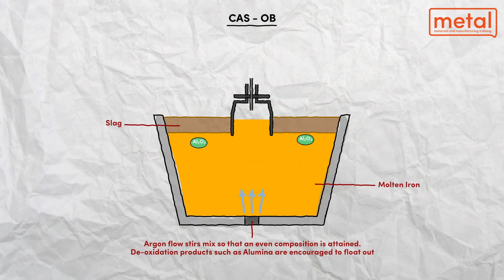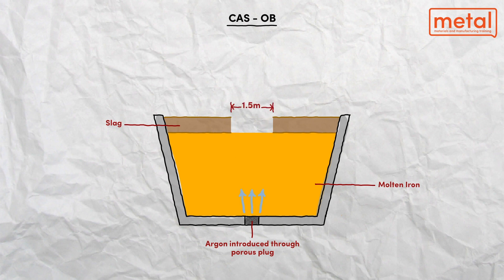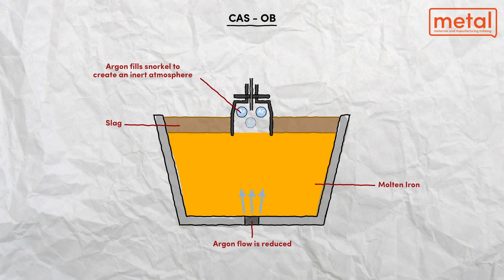After the delivery of the ladle to the liquid steel processing station, blowing of argon through the porous plug in the bottom of the ladle is started and the presence of purging can be visually monitored. Before the bell is lowered, argon flow is increased so that the surface of the liquid steel in the purge area has an open eye.